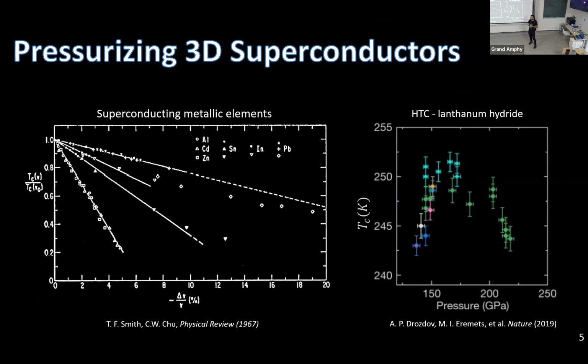Understanding what exactly pressure will do to your sample is very, very complex, because pressure affects many things inside your material: the phonon energy, the band, the density of states, and many other things. So we can see pressure has different effects in every material. Here we have the different effects that pressure can have on our systems. One of them is destroying the superconductivity, which we can see in superconducting metallic elements.